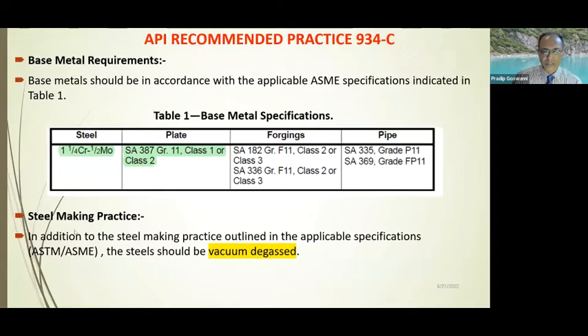The steel making practice is very specific. You need to have a very clean steel, and at the same time, the steel has to be vacuum degassed. That means basically to control all the tramp elements, number one, and then number two, to control the gaseous impurities in the steel, which can give rise to problems during fabrication or even during service also.